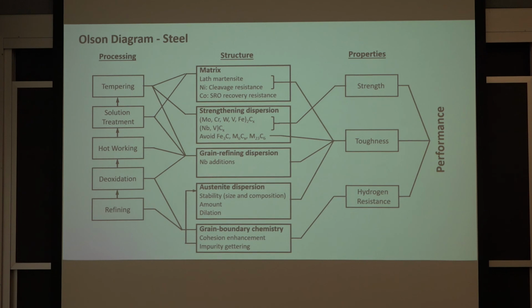Suppose we're looking for an even higher increase in strength. We want little grains, like we talked about, right? We talked about putting little grains in the material because that gives you a higher strength from the Hall-Petch relationship. How do you do that? It turns out that niobium in steel is a very, very effective grain refiner.